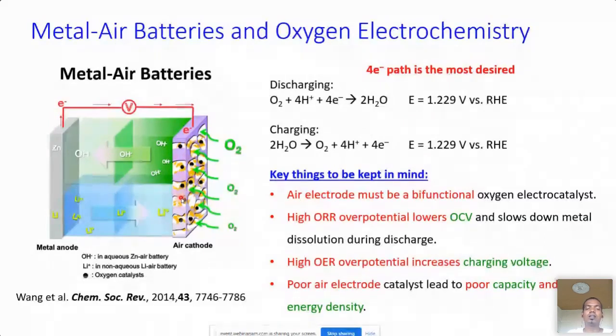If we assume the material is reducing oxygen exactly at the reversible potential, it will be 0.7 volts, and your lithium or zinc anode will be having some potential. When you calculate the cell voltage, it is going to be very, very low. So the 4 electron path is very important during discharge. Similarly, the 4 electron path is also important during charging, because if you increase the anode potential during charging, it is again going to cost you more energy, as your material is not performing water oxidation efficiently with lower overpotential. So we need a very good bifunctional catalyst for having a very good metal air battery system.